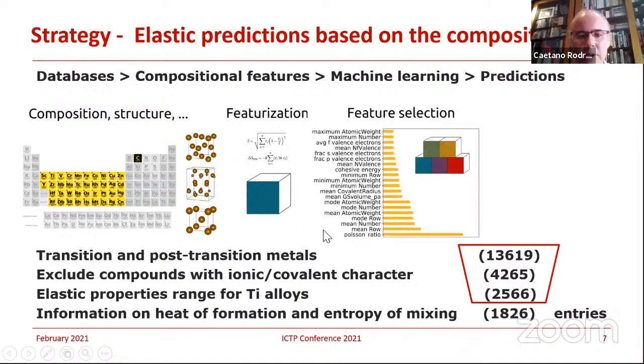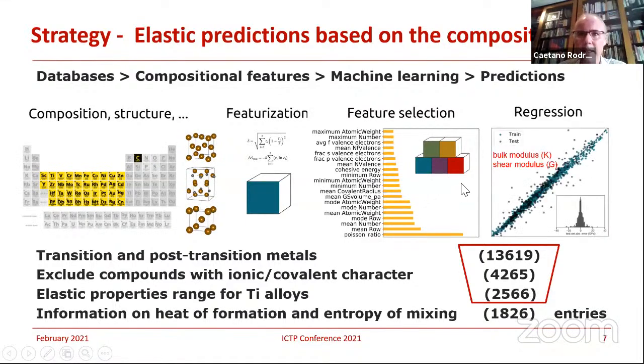Now, what you are looking for is to be able to predict the elastic properties based only on composition, so using this machine learning process. One important step in the exploratory part of the machine learning process is to look for which features will potentially be the best to describe a given target property. So to do that, you do a feature selection. You could figure out the best features that can let us have a model based only on composition. Finally, this has been fed to some linear models or random forest regressors in order to train a model towards the bulk modulus or the shear modulus, again using only the composition information. So this was more or less the step regarding the machine learning process.